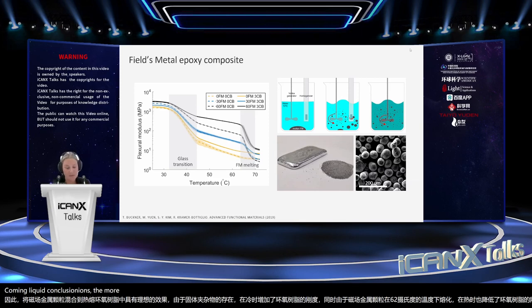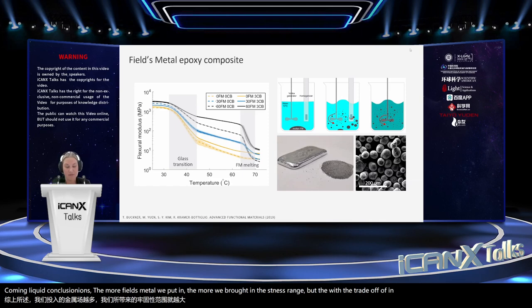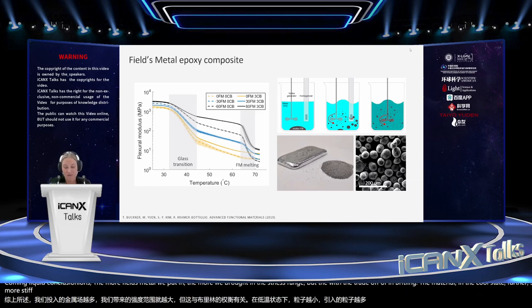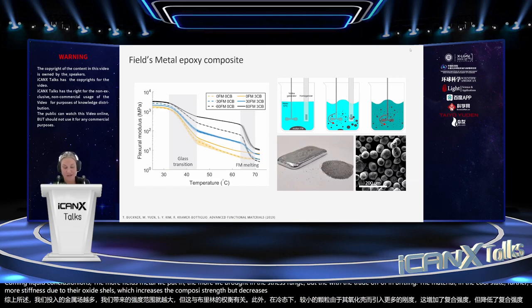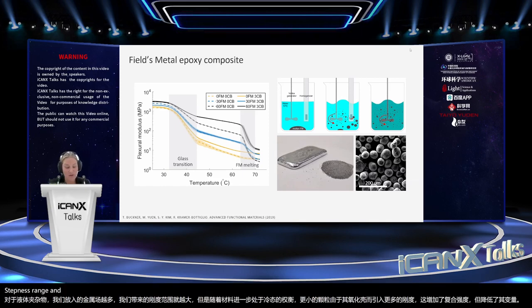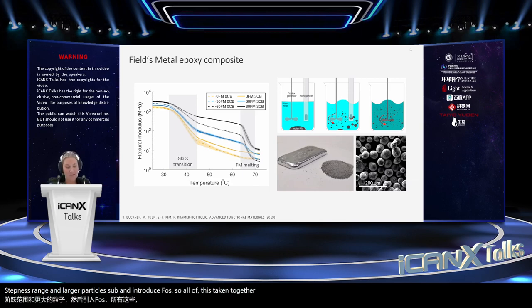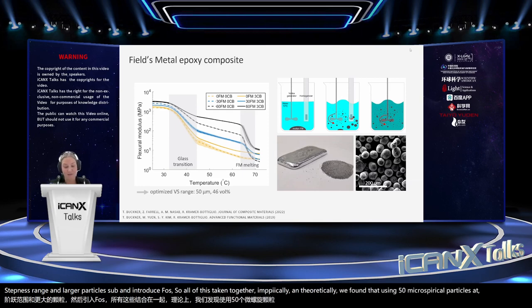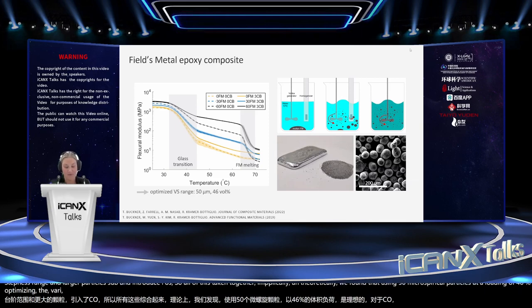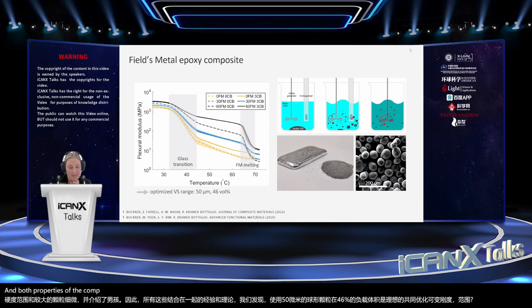The more Fields metal we put in, the more we broaden the stiffness range, but with the trade-off of embrittling the material in the cool state. Further, smaller particles introduce more stiffness due to their oxide shells, which increases the composite strength but decreases its variable stiffness range, and larger particles settle and introduce voids. So all of this taken together, empirically and theoretically, we found that using 50 micron spherical particles at a loading of 46% by volume is ideal for co-optimizing the variable stiffness range and bulk properties of the composite.